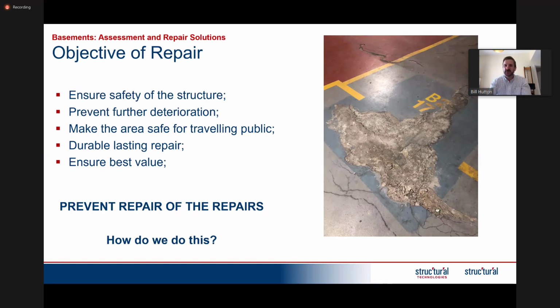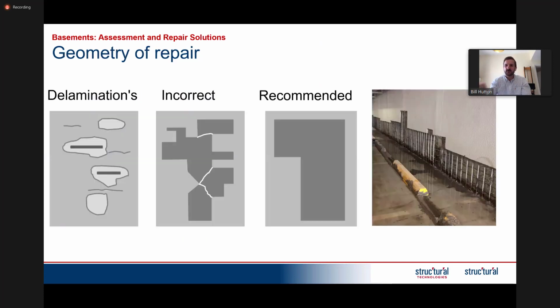Now we're just going to go through some basic steps of a conventional concrete repair that you as owners, whenever you're having repairs carried out in your structure, can check are being carried out, and they should help fulfill your objectives. First would be determining a suitable repair geometry. If you have delaminations as shown on the left, and you just sound those out with a hammer and follow the exact geometry of the delaminations, then you may end up with a fairly complex shape like we see in the middle.